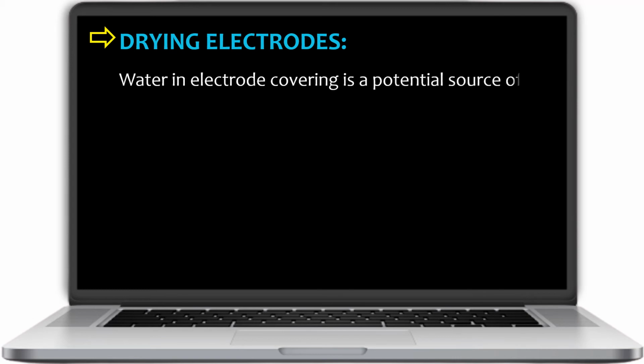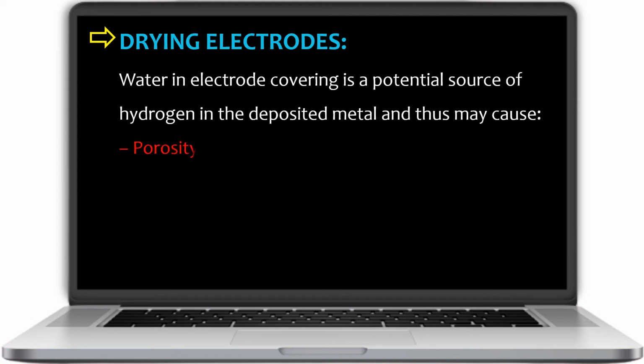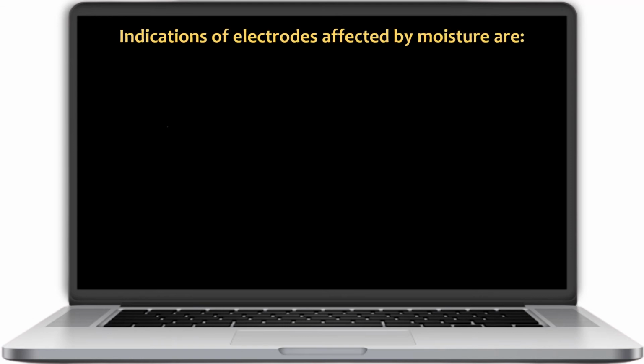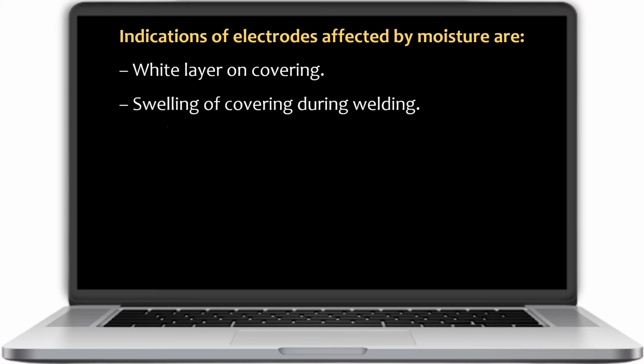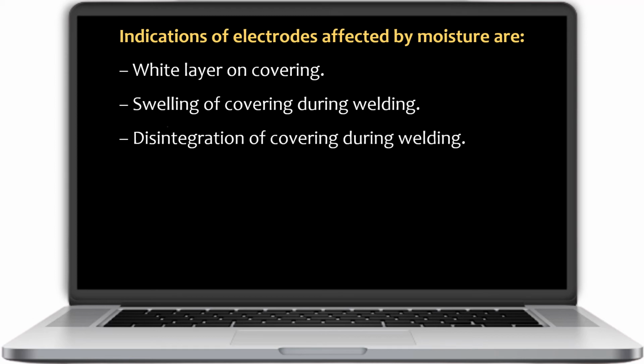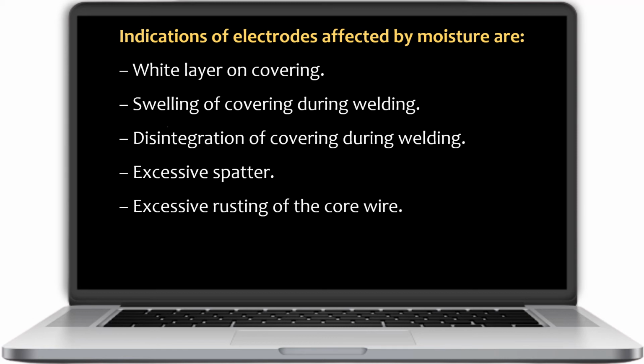Drying electrodes. Water in electrode covering is a potential source of hydrogen in the deposited metal, and thus may cause porosity in the weld and cracking in the weld. Let's see about indications of electrodes affected by moisture. White layer on covering, swelling of covering during welding, disintegration of covering during welding, excessive spatter, excessive rusting of the core wire.